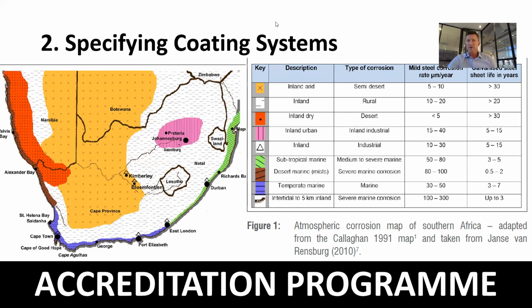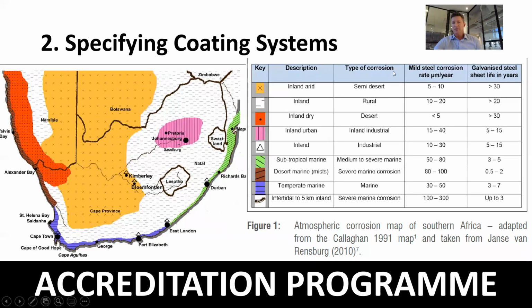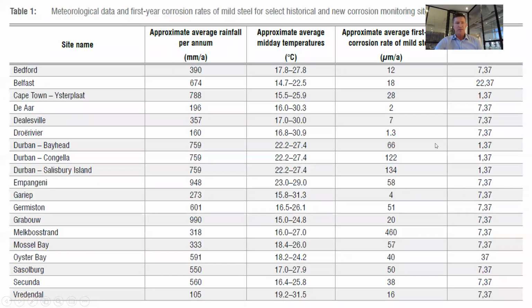Now you'll see on the far right of the table here, you've got types of corrosion, mild steel corrosion rates in micrometers per year, and then galvanized steel sheet life in years. And if you go down to the bottom, you'll see the intertidal to 5 kilometer inland, severe marine corrosion type. And you'll see the corrosion factor is from 100 to 300 microns per year, which is a hang of a lot. You can take your time to look through that in the recording.